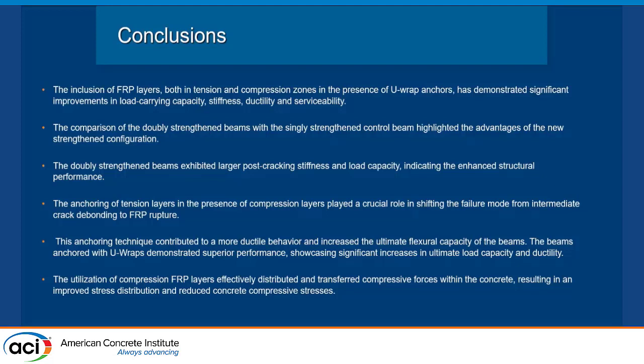So as a conclusion here, the FRP layer in tension and compression in the presence of the U-wrap could be a significant improvement for the load carrying capacity and the ductility and serviceability. The comparison of the doubly strengthened beam with a singly strengthened beam highlighted the advantage of the new strengthened configuration. So adding the compression sheet would enhance the behavior of the beams in terms of ductility and serviceability. This conclusion, we cannot see without anchoring the FRP.